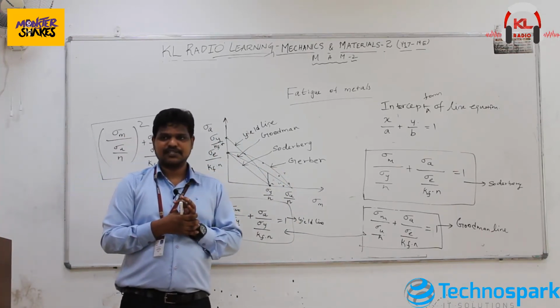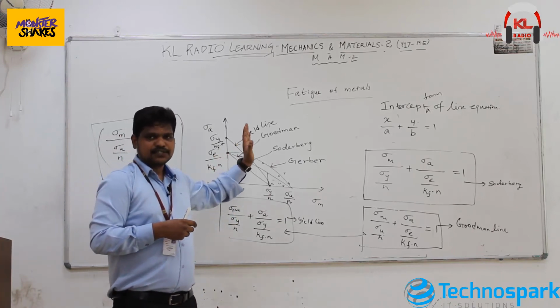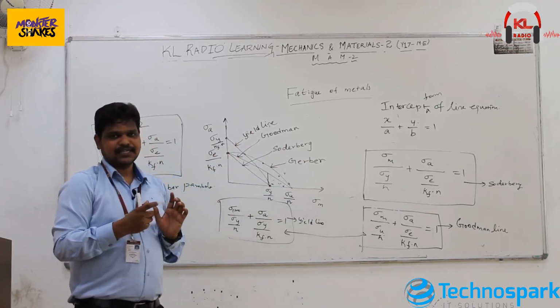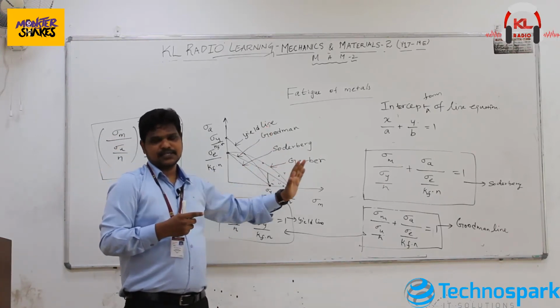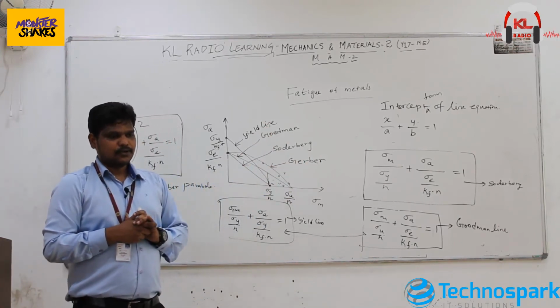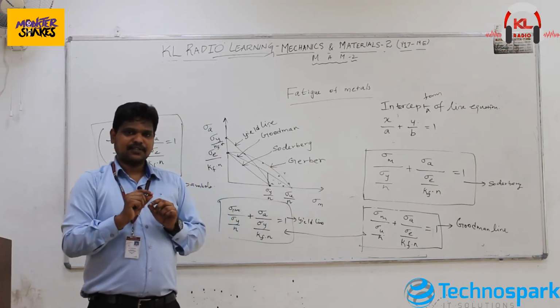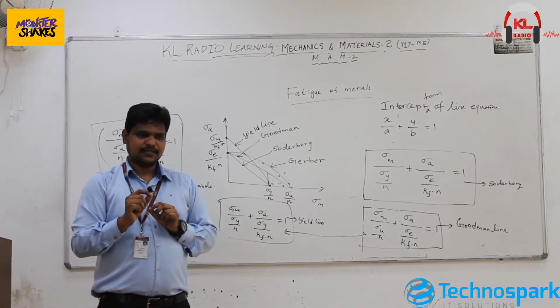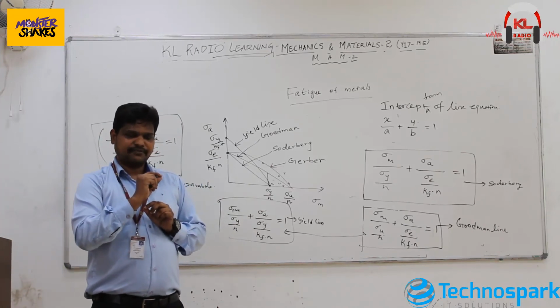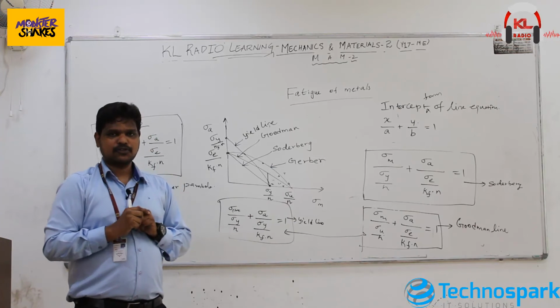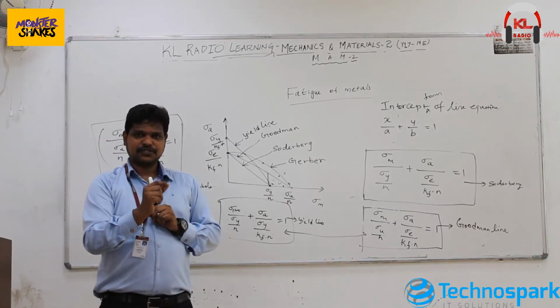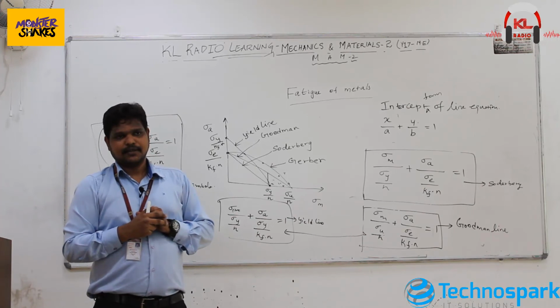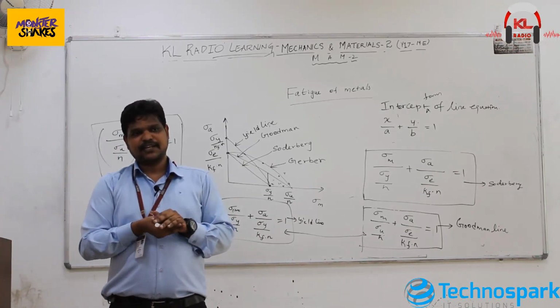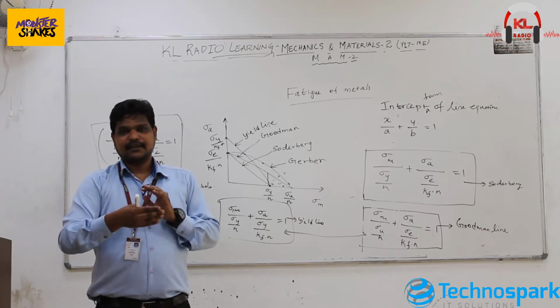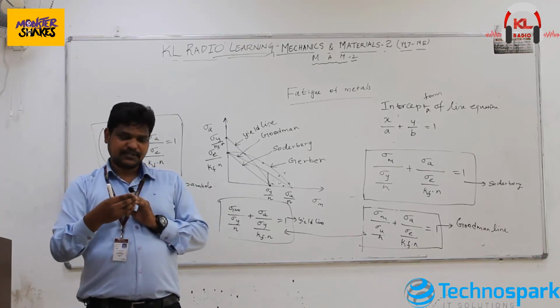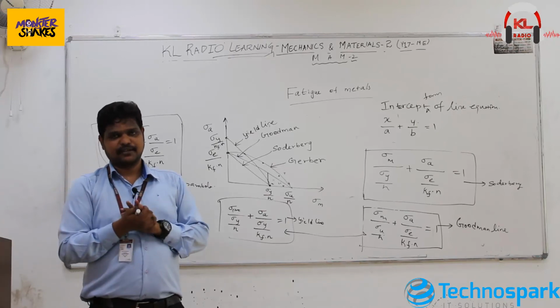For the first case of reverse stress cycle, I have drawn the stress versus number of cycles to failure curve, that is the SN curve, which is plotted between the alternating stress and number of cycles to failure. We noticed that after 10 power 6 cycles, the failure stress is almost constant. That stress level we choose as the endurance limit or the fatigue limit. For a machine component, if we maintain the stress below the fatigue limit, it can go for an infinite number of cycles without failure.